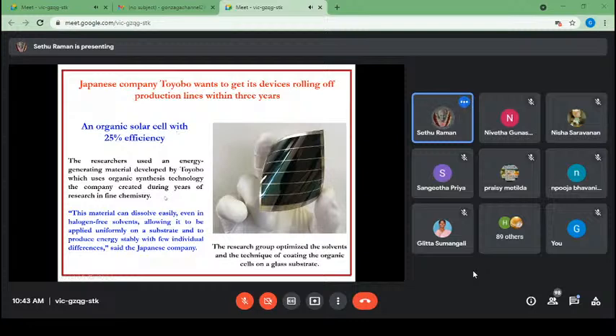They have not released what type of material they used for the fabrication of the solar cells, but they are saying this material can dissolve easily even in halogen-free solvents, so by using this material they achieved 25% power conversion efficiency. This research group optimized the solvents and the techniques of coating these organic solar cells on glass substrate, and also prepared them on flexible plastic substrates.